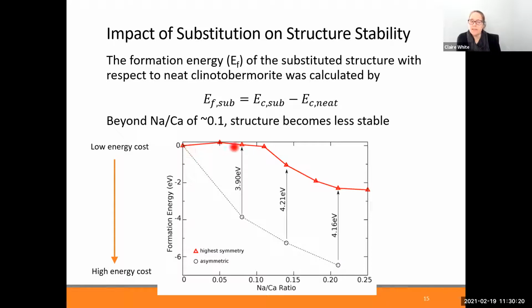So this is interesting, meaning that you can put some sodium in and be okay, but then there comes a point whereby the structure is just less stable overall. We think this can mean that if you want to incorporate sodium into a calcium silicate hydrate gel, you want to be careful with the amount that you put in there. Some is okay, a lot is not. This is helping inform us, when we look at experimental methods of investigation, what might be a cutoff limit for the amount of sodium that can be incorporated into these systems.